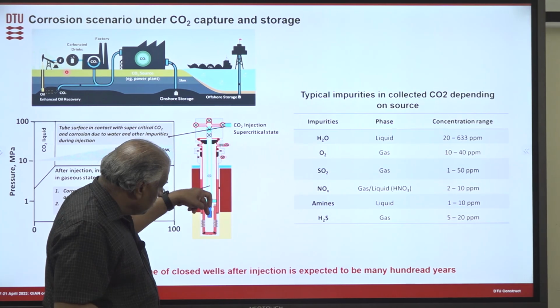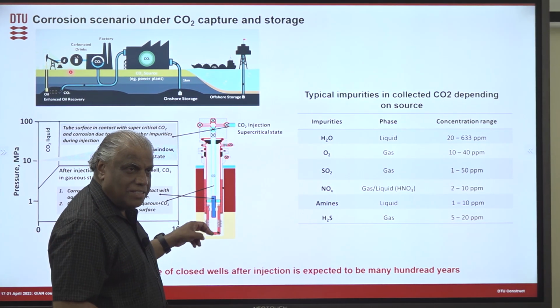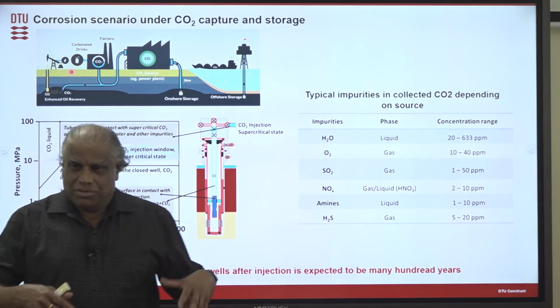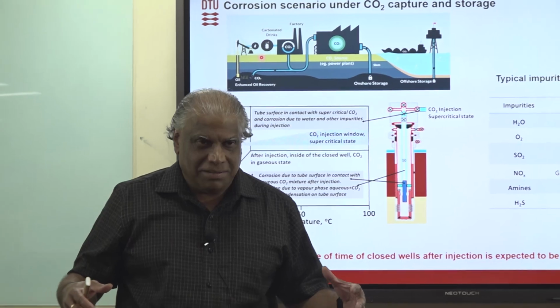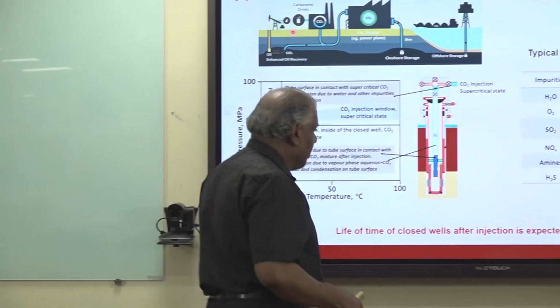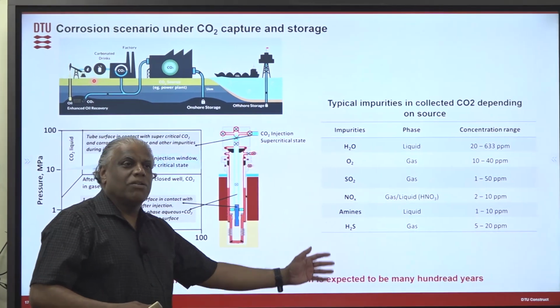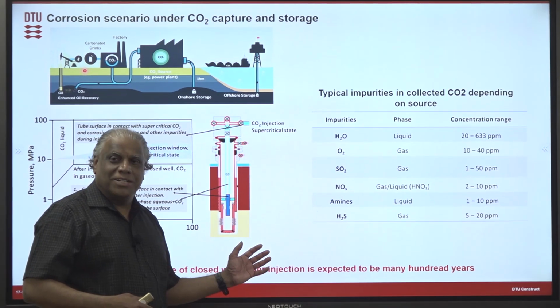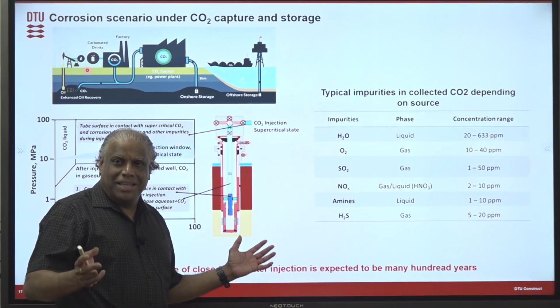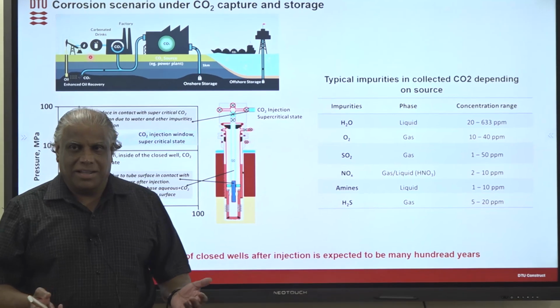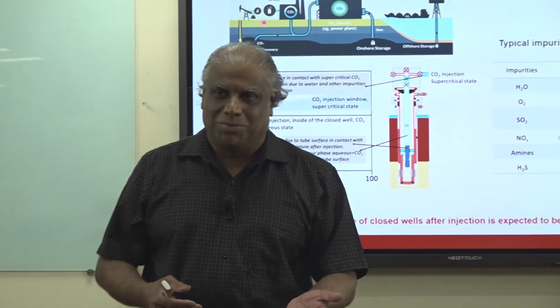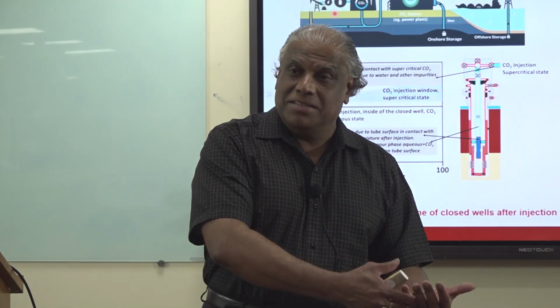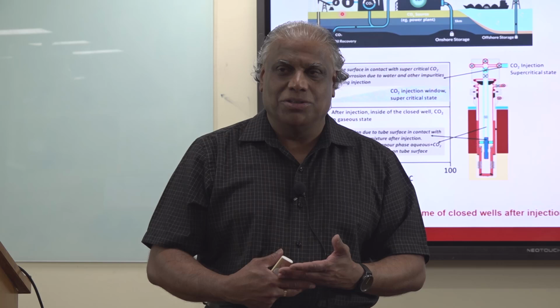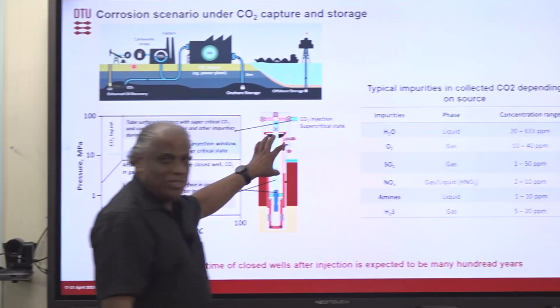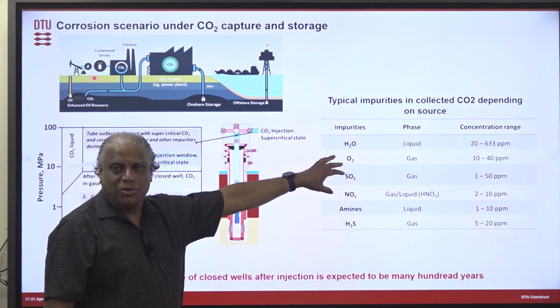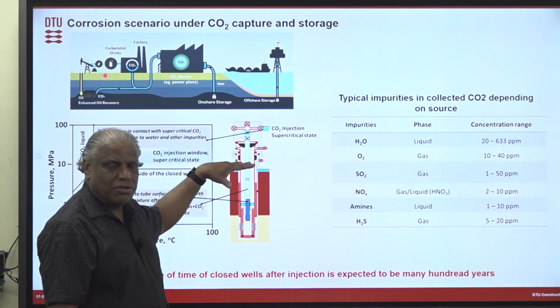Then the CO2 will go down, down, down, to the reservoir. During the flow, it will get depressurized, and once it reaches the reservoir, it becomes gas. But then there is a lot of water in the reservoir. So once it reaches the reservoir, it becomes soda. Like that, CO2 is dissolved in the water and it becomes like carbonic acid. Then you have another corrosion problem, carbonic acid, because now it is aqueous phase CO2, an aqueous phase which is saturated with CO2. Here it is a CO2 phase which is saturated with a little bit of water. So this is a corrosion issue, and this is also the complexity of the corrosion.